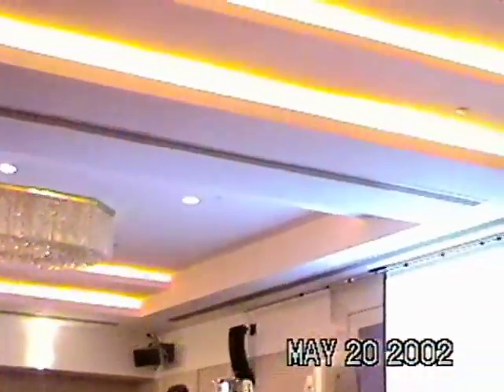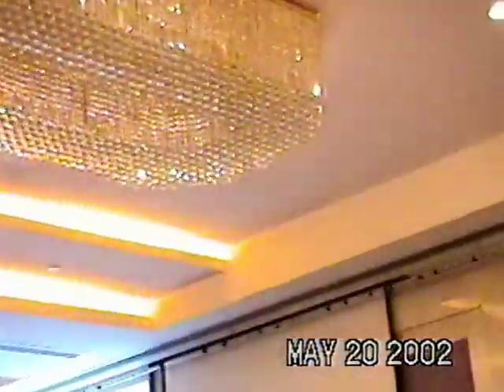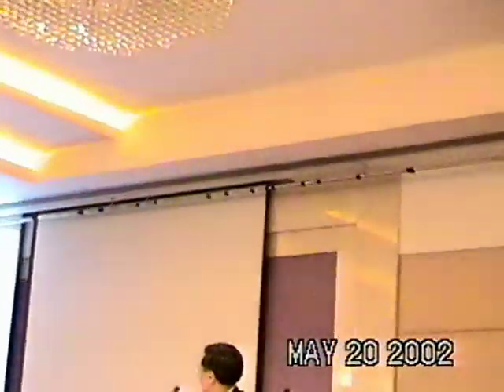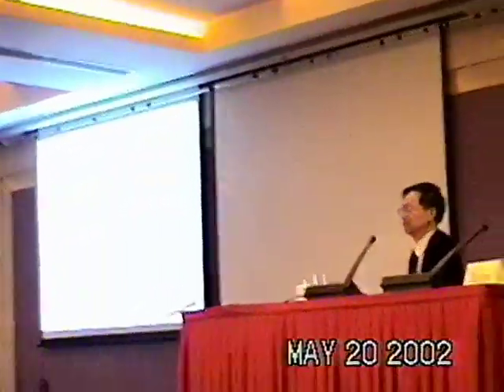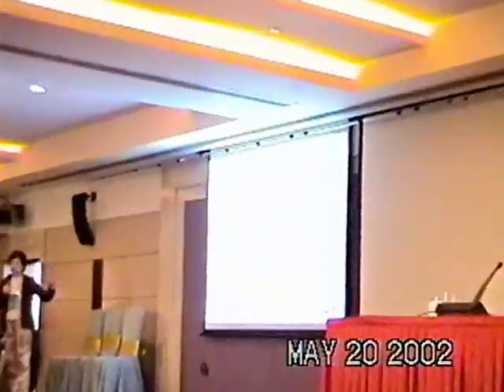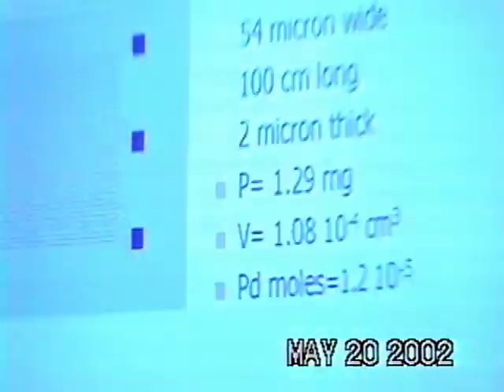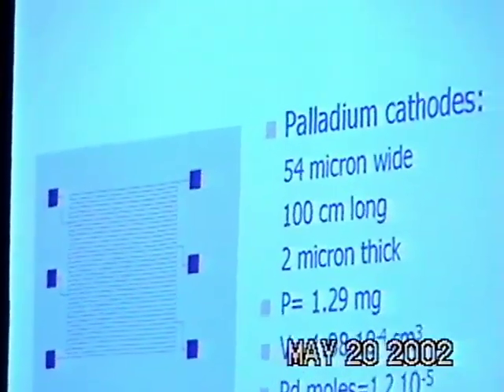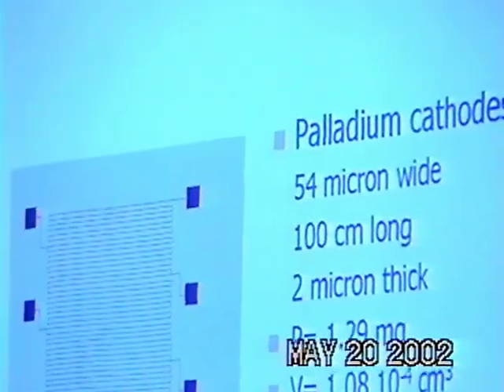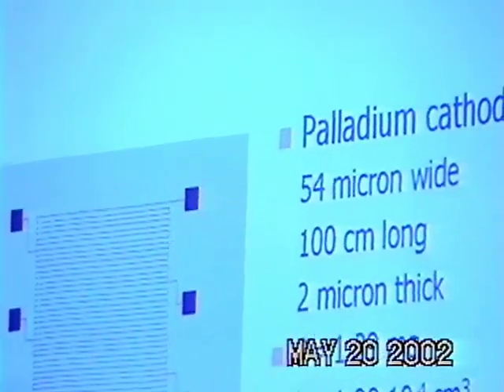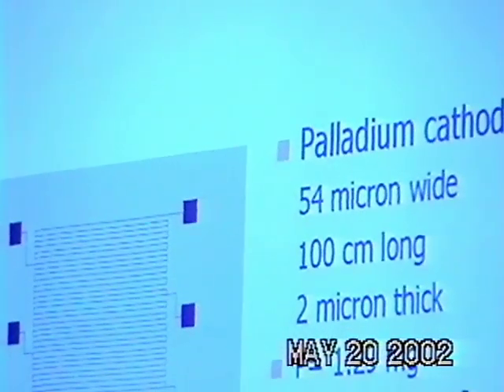This is the geometry we chose to prove this effect. This is a palladium cathode. It's a thin film deposition on different substrates, and the dimensions are written down there. As you can see, it's a very tiny structure, 2 microns thick, 54 microns wide, and 100 centimeters long.